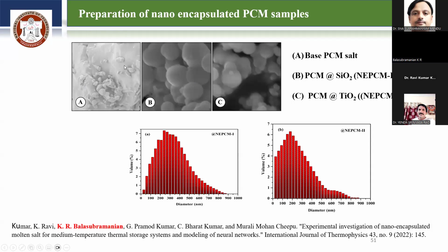Here we can see it is like a flake, right, for the base PCM salt, whereas here it is spherical in shape, which shows the formation of nano encapsulated PCM samples. And here we can find the size of the SiO2 based PCM and TiO2 based PCM, which ranges between 200 to 500 nanometers.